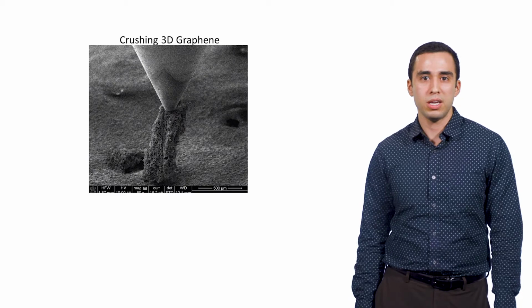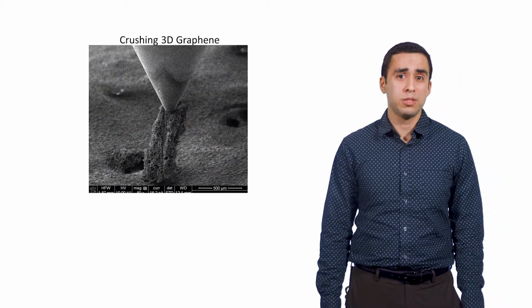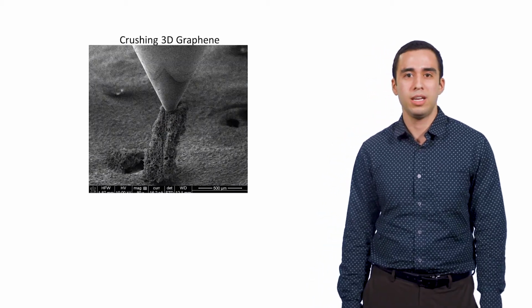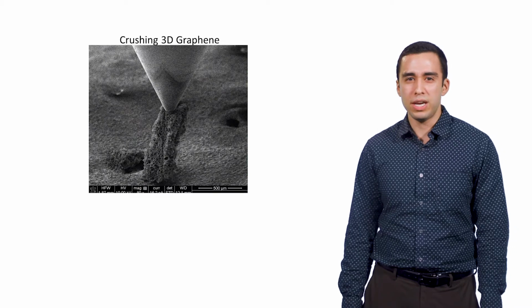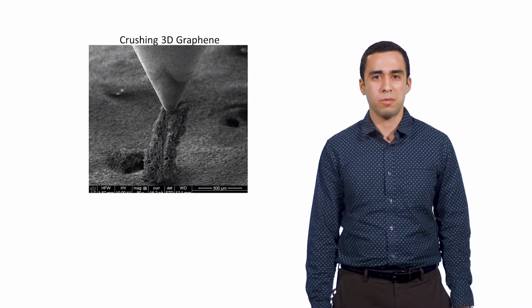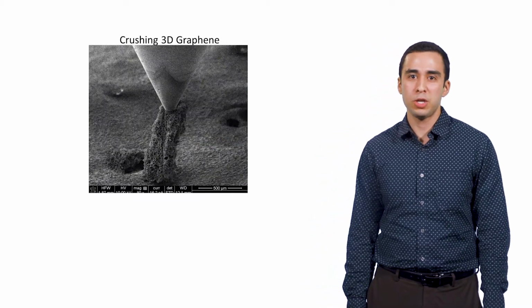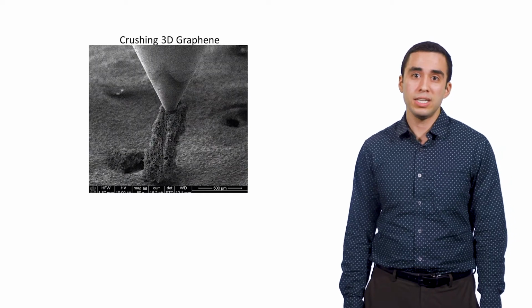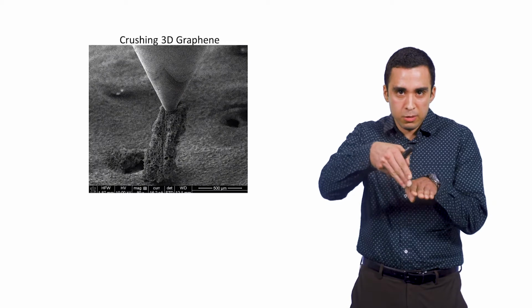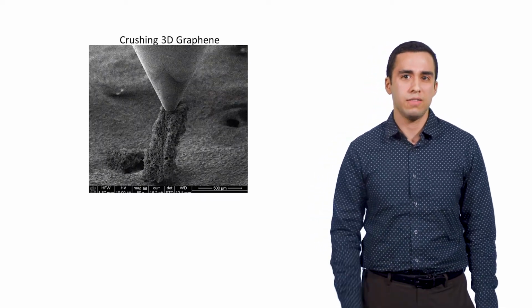Due to our high-quality processing, our 3D graphene mechanical strength is about 4 times as strong as other graphene foams and 1,000 times as strong as graphene oxide foams. Yet, with this great improvement, our sponges are still 150,000 times weaker than graphene's max theoretical strength. Even with our careful attempts to make the purest graphene possible, we still end up with polycrystalline graphene, papers stacked side by side with their edges fused together, which makes the structure weaker and not as electrically conductive as true single-layer graphene.